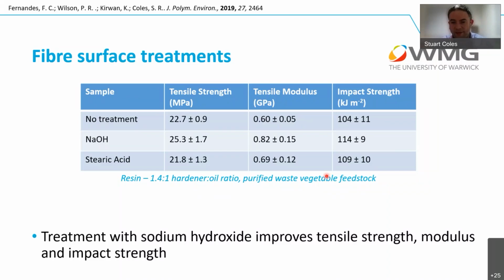Whilst we did have not a great result in terms of the tensile modulus, the sodium hydroxide gave it a little bit of an increase. Tensile strength was largely the same, give or take a few percent. It was difficult to really identify whether or not we were having a really significant effect. The stearic acid didn't really help with the mechanical properties. It did help with the water absorption. Coating the fibers with stearic acid did give us a significantly lower water absorption from the fibers.